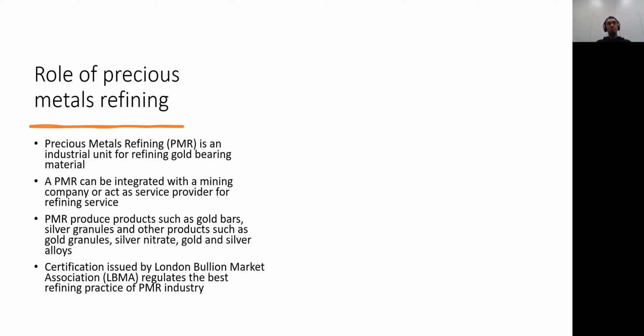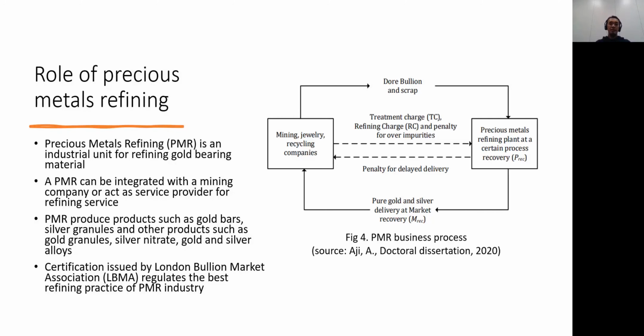So they put some kind of regulation, for example, that a marketable pure gold should contain not less than 99.99% of gold. So that is the minimum content of a gold bar. And for silver, pure silver cannot be less than 99.5% of silver. So those kinds of regulations take place for this business.